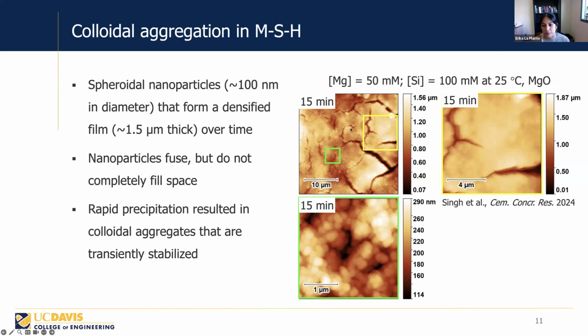We could also notice that the film is not completely filled in. There are gaps, there are crack-like features. So these nanoparticles fuse, but they do not appear to completely fill this space. So this shows us we have this rapid precipitation of this phase, and then you have these colloidal aggregates that are stabilized transiently.